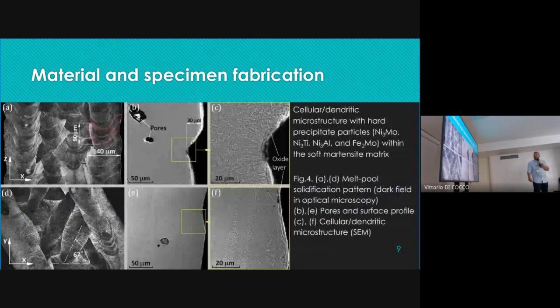On the left side of the slide, you can see the path of the laser. Actually, on the specimen, you can see the contouring. It's hard to see, but on the outer layers of the specimen, this is the 0.5 millimeter wall. You can see the 67 degrees on the bottom, and you can see the lines of contouring. But what was the biggest problem? Also, you can see the porosity, but the biggest factor for the fatigue crack initiation was the places where the specimen was a bit thinner, these valleys. They were like 30, 40, maybe sometimes 50 micrometers deep on both sides. On the outer and inner layers, there was not really a big difference, and at the end, the specimen fracture was almost always in those valleys, and most often from the outer layer, but maybe that was just a coincidence.